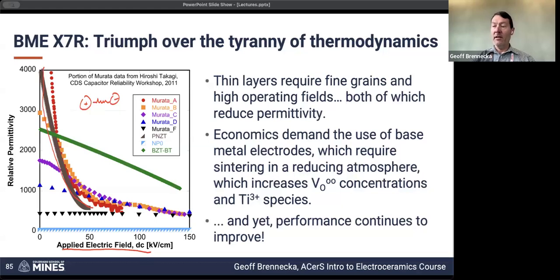So what that really means is that now we've got a grain size effect to deal with, plus as we get thinner, the same voltage leads to a higher electric field. A higher electric field leads to a lower permittivity. So everything we're doing to scale things and make the physical size smaller is actually making the performance worse. But we need both.